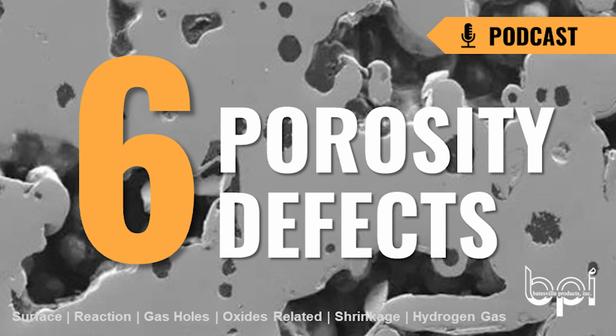But the key is, as Ernie just said, it's localized. It's going to be in the area where the turbulence is. If it's hydrogen, it's something in a melt, and it's going to be throughout the whole casting. You're not going to be able to fix an issue unless you can identify it. So that's why we're talking about the different types of porosity and the different characteristics.